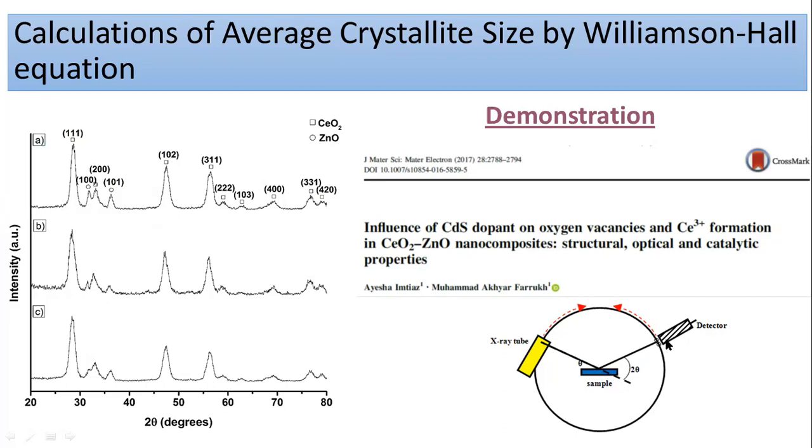And when it is diffracted, if you take the angle from the incident X-rays, it would be the 2 theta, double this one, because for the constructive interference, this should be equal to this. So the diffraction angle should be half of the 2 theta. Actually, this we are going to consider for the calculation of the crystallite size, but the instrument is going to give you the 2 theta value. That is the reason why we are going to convert the 2 theta into the theta values.